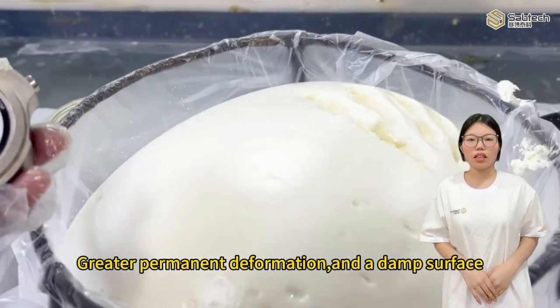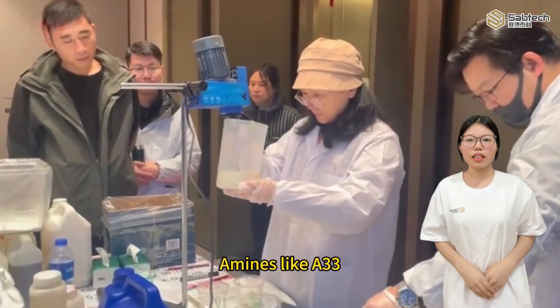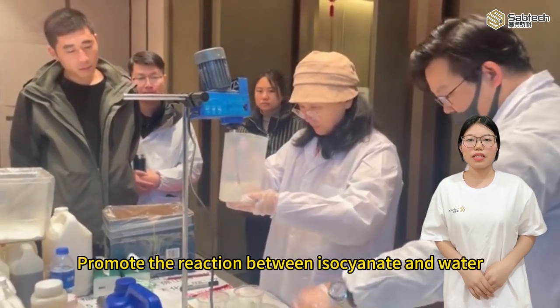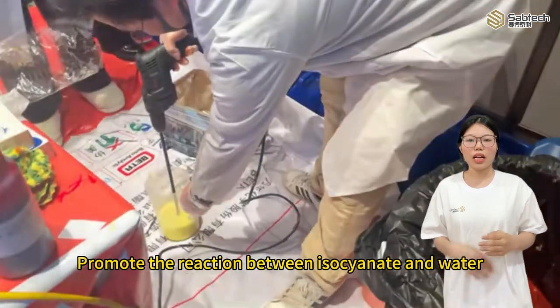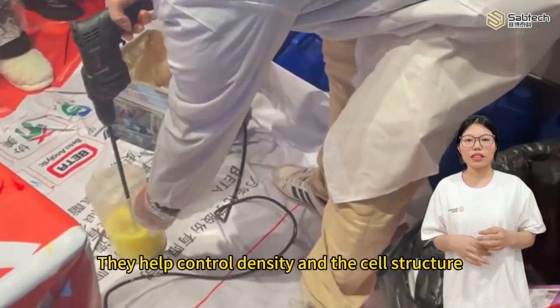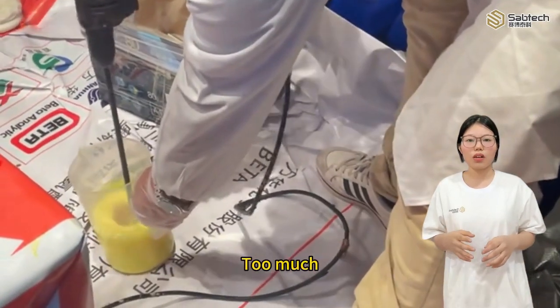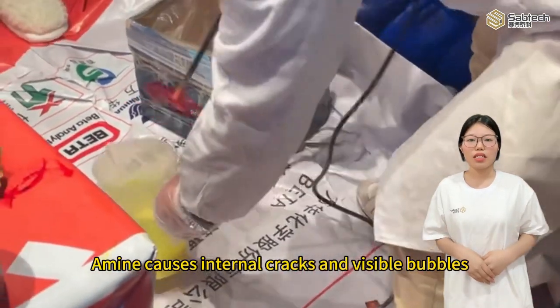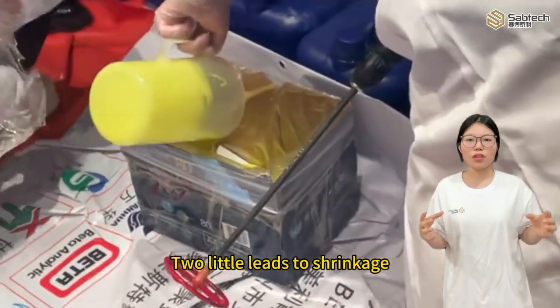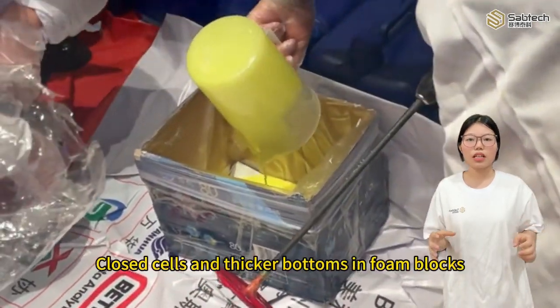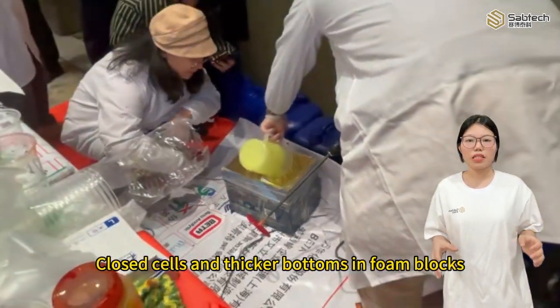Fourth, catalyst. Amines like A33 promote the reaction between isocyanates and water. They help control density and the cell structure. Too much amine causes internal cracks and visible bubbles. Too little leads to shrinkage, closed cells, and thicker bottoms in foam blocks.